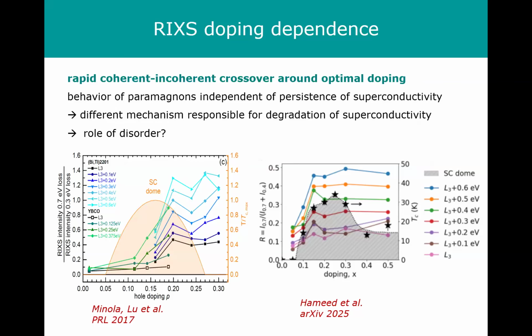Okay, and this is sort of the concluding picture here. On the left-hand side, our old data on thallium here and YBCO show that this crossover between Raman-like, so collective paramagnon type excitation, to more incoherent particle excitations is rather rapid around optimal doping. Okay, and the data on the lanthanum calcium copper oxide are, to within the error, identical to those in the other systems, despite the fact that superconductivity persists to much higher doping levels.